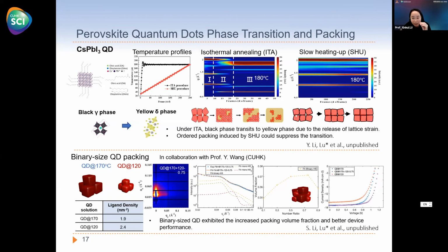We find this is related to the packing, the heat during the packing. The quantum dot tends to pack in a more ordered structure. This will increase the lattice strain inside the perovskite quantum dot, which suppresses this unwanted transition. So in the following work, we try to pack the quantum dot film as dense as possible by mixing two different sizes.